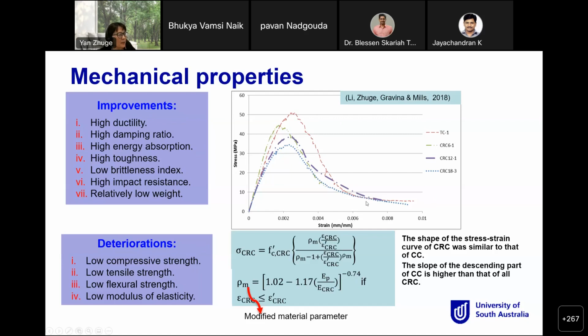crumb rubber concrete, because without this curve you cannot do finite element analysis, and you cannot give a proper design formula. This work has been published, with a lot of citations, in, I think, Construction and Building Materials. We have developed modified material parameters to consider the percentage of crumb rubber, and this formula can predict the failure pattern of crumb rubber concrete very well when compared to different tests. Those are some testing results, and based on them we found this formula.